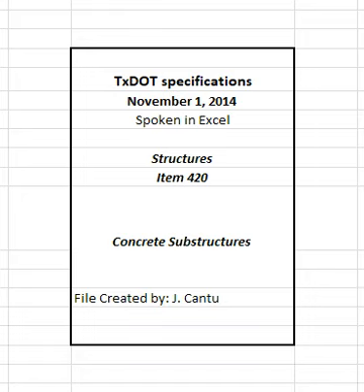Do not place concrete in contact with any material coated with frost or with a temperature of 32 degrees Fahrenheit or lower. Do not place concrete when the ambient temperature in the shade is below 40 degrees Fahrenheit and falling unless approved. Place concrete when the ambient temperature in the shade is at least 35 degrees Fahrenheit and rising or above 40 degrees Fahrenheit. Provide and install recording thermometers, maturity meters, or other suitable temperature measuring devices to verify all concrete is effectively protected as follows.